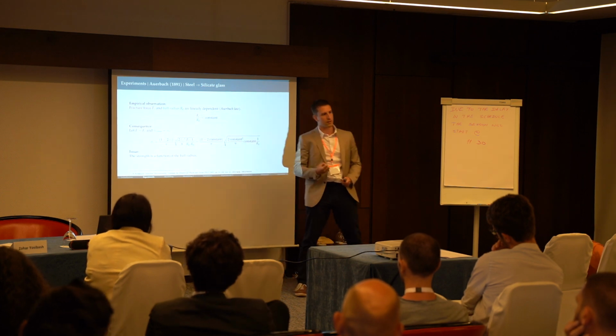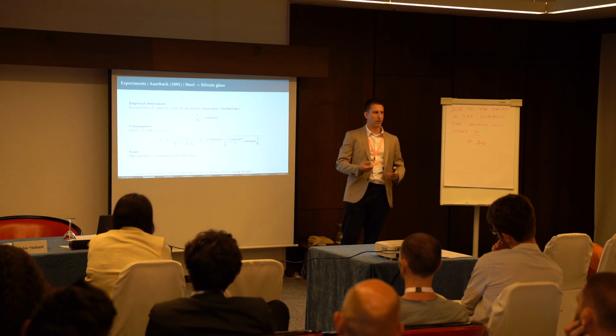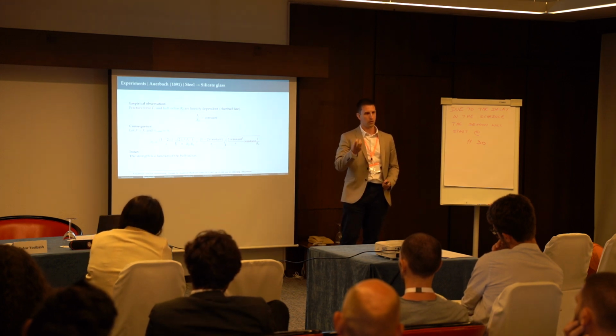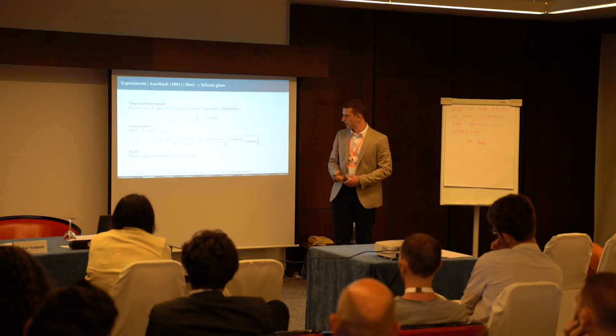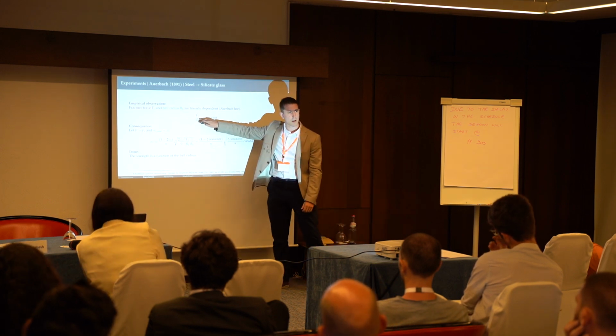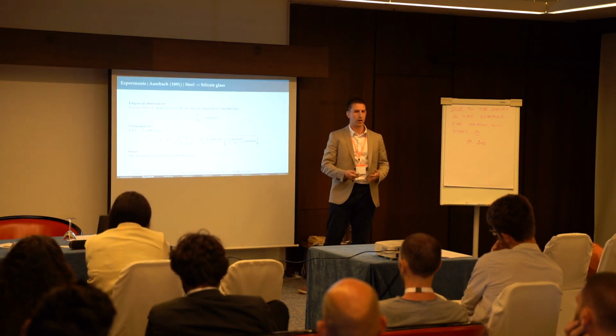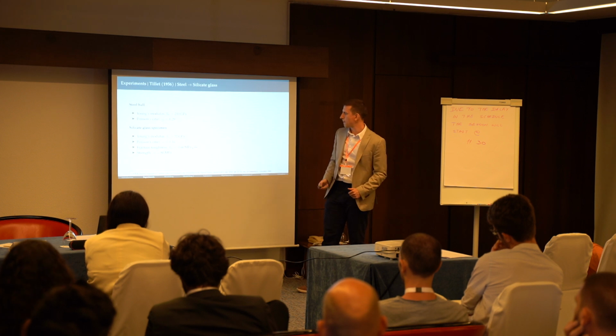That means the strength, it's a paradox, is not a material property, but it's a function of the ball radius, a function of the indentation, which doesn't make sense. If it was a function of the square of the ball radius, then everything would be constant and strength would be like a material property, which is constant.